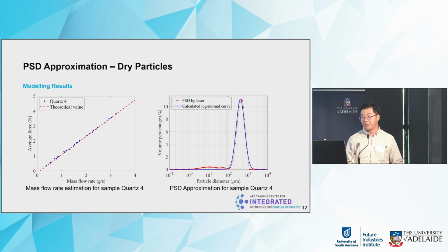On the left-hand side is the relationship between the sensed average force and the mass flow rate. As can be seen from the figure, there is a high agreement between the average force and the mass flow rate. There is a linear relationship, and the red dashed line is the predictive model that we developed based on impact mechanics. The right-hand side figure shows the modeled particle size distribution based on our model and the sensing signal. The red dots are the benchmark measured by the Mastersizer 2000, and the blue curve is the one that we modeled with a pre-assumed log-normal distribution.